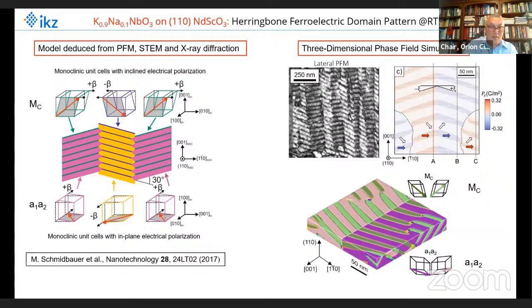And the very nice thing is now that when you perform three-dimensional phase field simulations, you end up exactly with the same model. You also here see the herringbone pattern consisting of MC phases, and the A1, A2 phases shown at the bottom as pink and violet colors. So we have a very, very nice agreement between theory and experiment.